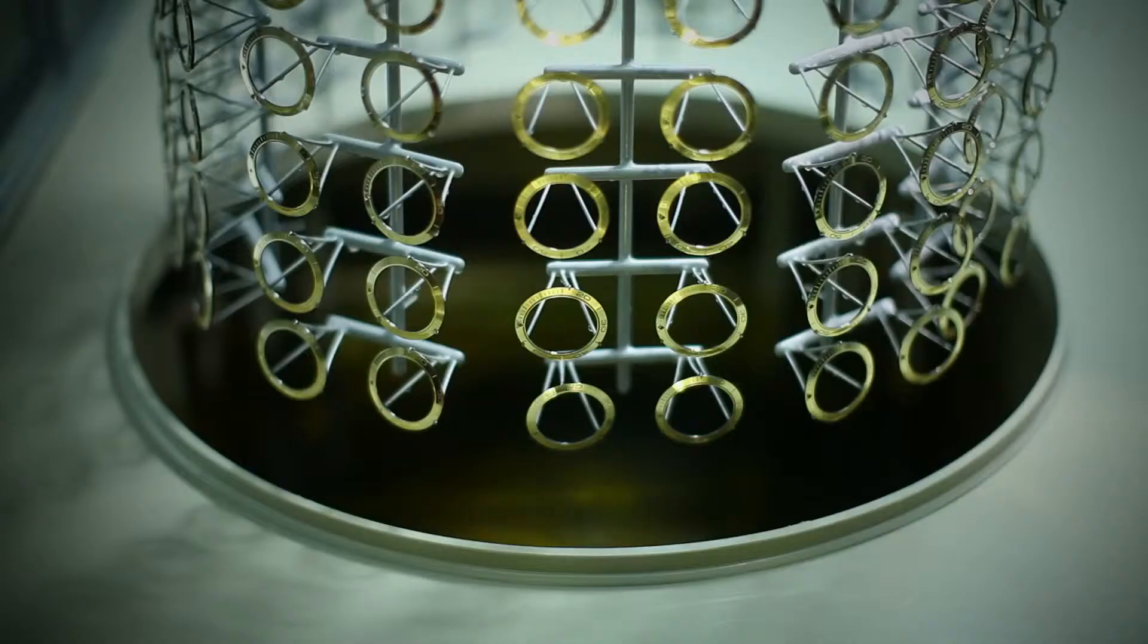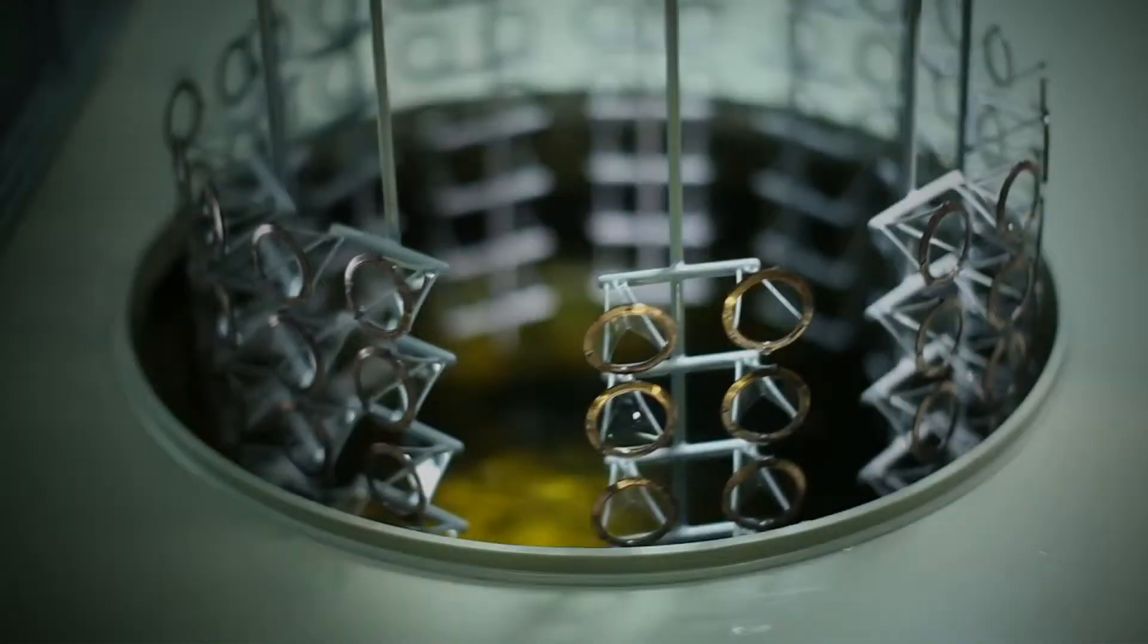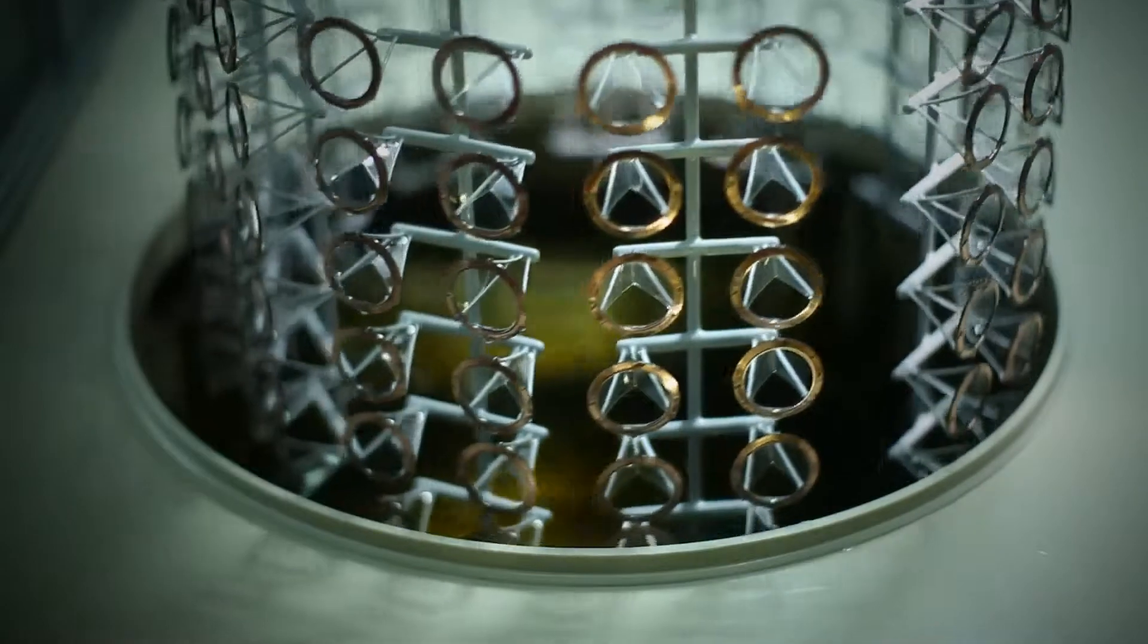The now-conductive ceramic rings are placed on a rack and submerged in a gold electrolytic bath for 48 hours. A thick layer of 18 karat red gold is formed that coats the ring's top surface. When the rings are extracted from the bath,